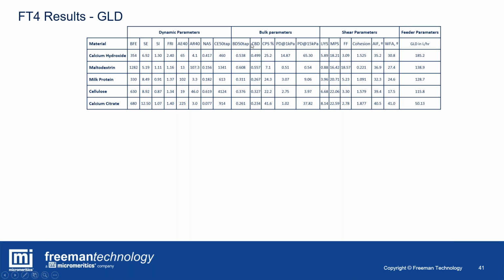Then we quantified bulk and tap densities. We measured the compressibility and the pressure drop. And then with the shear testing, we measured unconfined yield strength and major principal stress. From that, we could calculate and derive flow functions, cohesions, and angle of internal friction. And then with the wall friction test, we could measure the wall friction angle. All of these parameters, the majority of this table, are from measurements from the FT4.